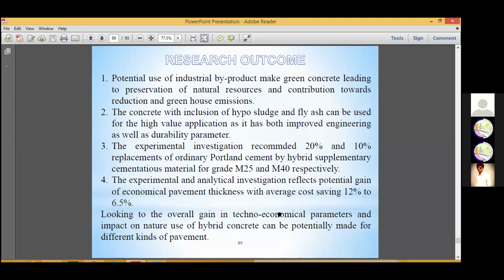The experimental investigation recommended 20% and 10% replacement of ordinary Portland cement by hybrid supplementary cementitious material for M25 and M40 respectively. The experimental and analytical investigation reflects potential gain of economical pavement thickness with an average cost saving of 12% to 6.5%. So looking at the overall gain in the techno-economical parameters and impact on nature, hybrid concrete can potentially be used for different kinds of pavement.